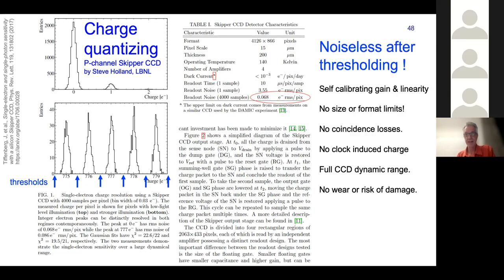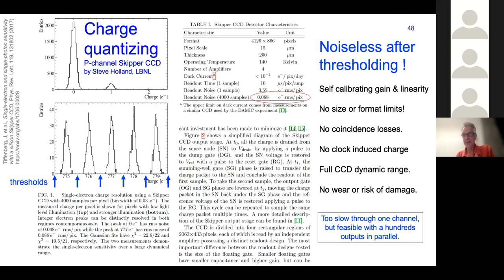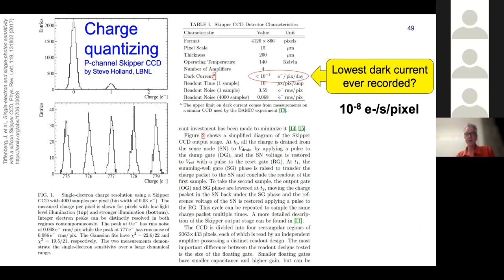Another remarkable feat is that if you look up here at the dark current, you'll see that the dark current's actually setting a world record. But first, let's just note, this is self-calibrating. You can tell the gain because you just count the electrons. Just make a histogram of a flat field and you know the gain and the linearity because you just look for the peaks in the histogram. No size or format limits, no clock-induced charge because you're reading out so slowly. Whole dynamic range doesn't wear out. It's amazing.